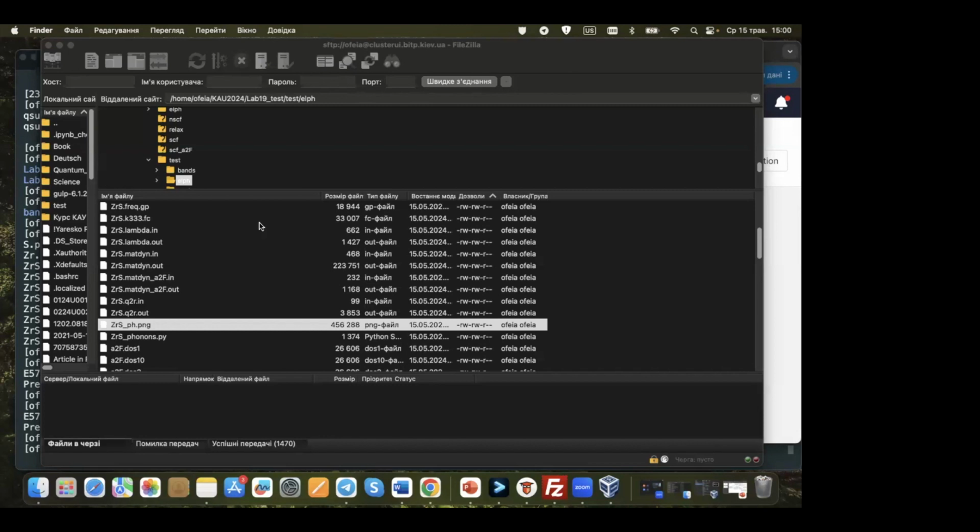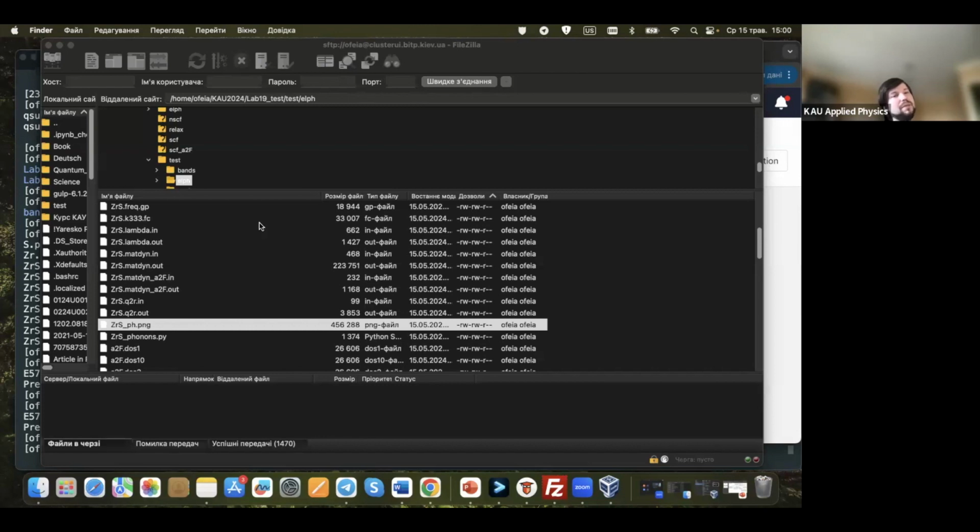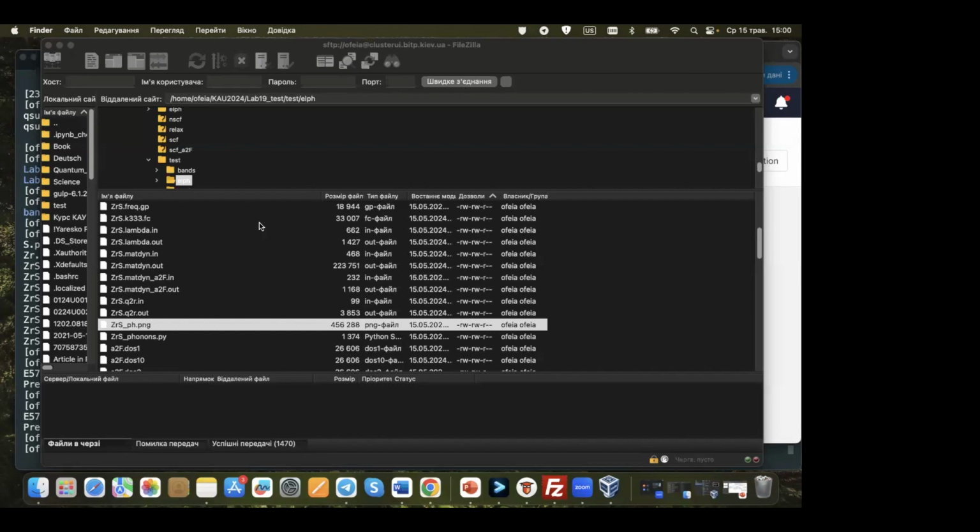Yeah, maybe you should also increase the Q point mesh. Maybe we should make better calculations, because you see we made our relaxations with an 8x8x8 k-point mesh, but for SCF we moved to 12. When we do this, some stress should appear on our cell. And as I told, for me, for example, the stress wasn't completely relaxed.